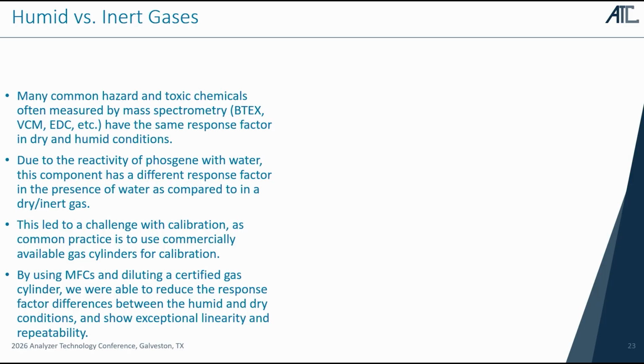Most common hazardous and toxic chemicals measured by the mass spectrometer, such as benzene, toluene, xylene, vinyl chloride monomer, have the same response factor in dry, inert gases from a calibration bottle and when exposed to ambient air humid conditions. Due to the reactivity of Phosgene with water, this component has a very different response factor from a calibration gas to exposure to humid ambient gas. We were noticing about a 30% difference in response factor between calibration gas in nitrogen versus calibrating with clean dry air or zero air.